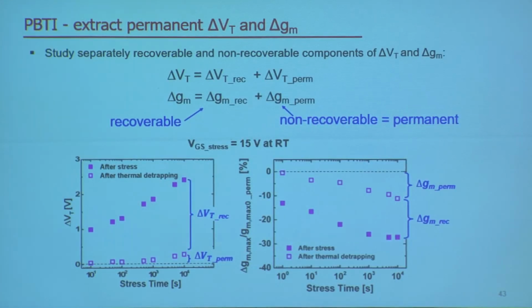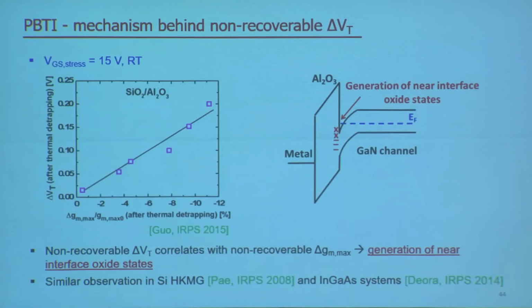So to study this permanent phenomenon and also distinguish that from the total VT shift that we measure, what we do is that in a typical experiment, we capture the total VT shift and GM degradation, and then we bake the device with thermal detrapping, and we extract the permanent portion. And then the difference between the two values will be the recoverable part that I have reported to you earlier. So through this process, we're able to only look at the permanent degradation.